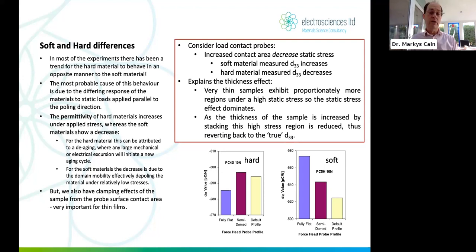So when we consider load contact probes, we know that increased contact area decreases static stresses. Okay, so increasing contact area, we're going from a point contact to a flat, therefore the stresses are going down. Now the soft material, the measured d33 increases, and that's this graph down here, this plot down here. Okay, but for a hard material, the measured d33 decreases, which is interesting, isn't it? But it's probably related to the fact that permittivity is changing in this way.